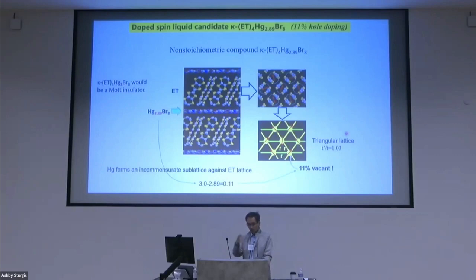Let me move on to the result. This is a doped system, so this is the main subject here. The material has the same layer structures, and in the two-dimensional conducting layers, the molecular arrangements are modeled as an anisotropic triangular lattice. But the ratio t'/t is 1.03. So the nearly regular triangular lattice is realized in this material as well.